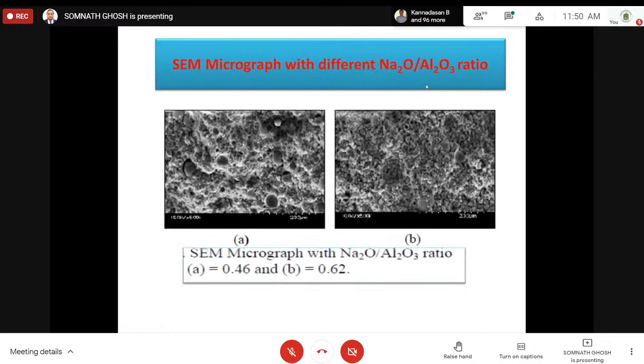Now you see here with different sodium alumina ratio, one is 0.46, the other 0.62. Right? It's much more dense. So from your result, you will get that it will absorb more water. That means the micropores are there, much more compared to this. So if this changes, how the microstructure is changing, that one should understand. That is why this kind of test is very important.